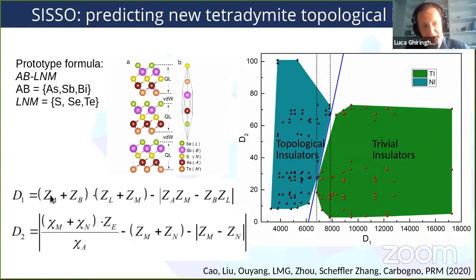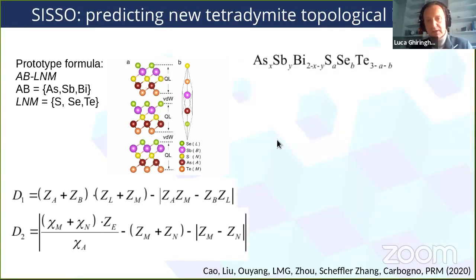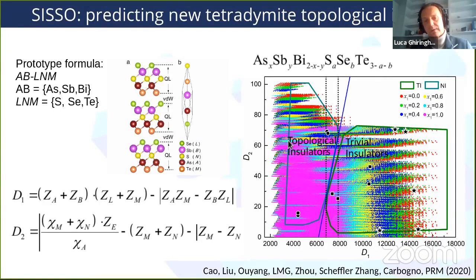And the input information is just the atomic number Z for A, B, and so on, and the electronegativity chi for M and N. So this formula is quite nice and symmetric: A, B, and then L, M, and then you have this difference with, again, A, B, and L, M, so it doesn't depend on, for example, the N. And this comes out from the algorithm. We didn't impose any symmetry. So this descriptor was selected and it proved to be a very good one. Then we exploit this model by saying, okay, now let's construct layered materials by having some kind of fractional occupation of the sites, and we can scan the whole material space that has millions of possibilities.